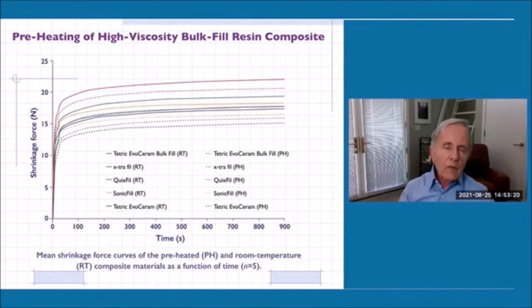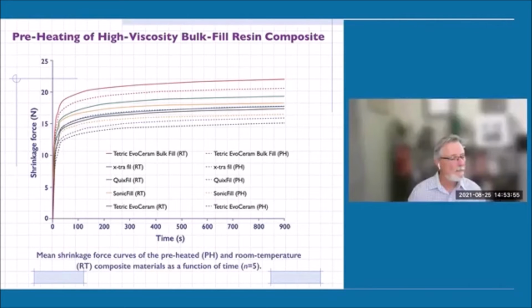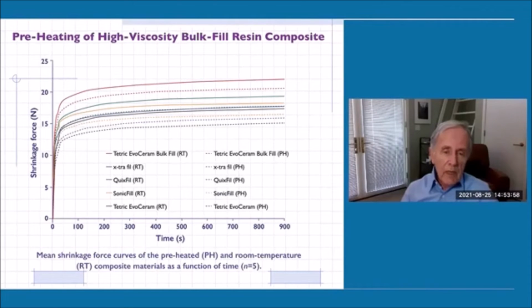With the advent of bulk fill materials, people have asked the question, does this preheating effect also extend to bulk fill material as it does with normal composites? And the answer is it does. This was a study that looked at 5 different bulk fill composite materials. The RT refers to room temperature in this graph, and the PH refers to preheated. And what we see here in every single case, for every single material, anytime the material was preheated, the shrinkage force was less. And that even extended to sonic fill, which was designed to be vibrated.